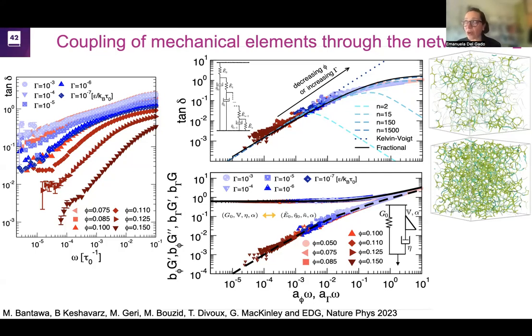what is the microscopic origin of these time scales and these energy scales that we have to put in. And we realize that we can demonstrate that they are associated to a hierarchy of mechanical elements that constitute the response of my gels. And this hierarchy of mechanical elements comes from the way the gel forms, but they are not easily visible in the structure, because the structure is actually too complicated to see that.